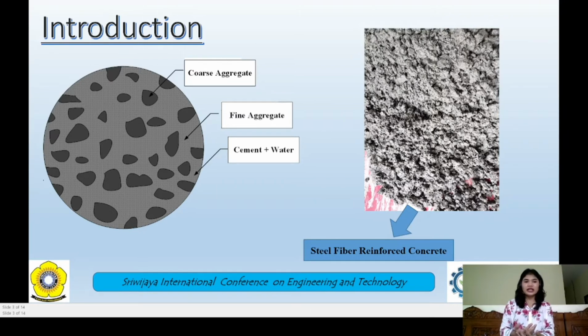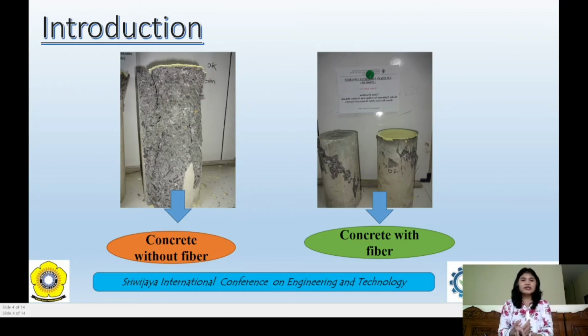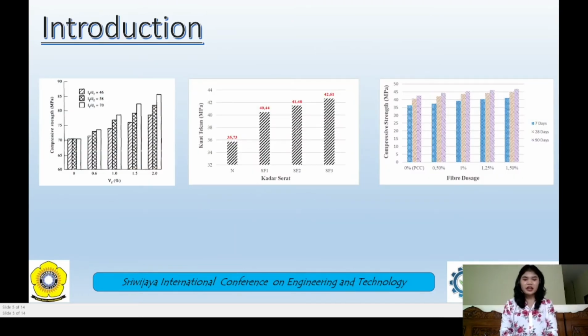Steel fiber reinforced concrete is a type of fiber reinforced concrete that uses steel fiber in its mixture to strengthen the concrete. A good composition of fibers in concrete can produce a composite material with an ability to reduce the crack width and increase the flexural strength of concrete. However, the fiber type and content used in the mixture affect the workability of concrete. Some investigations have found that the compressive strength of concrete increases with the fiber content used. The use of fibers with different lengths can significantly improve the mechanical properties of concrete by increasing the compressive strength by about 10 up to 32%.